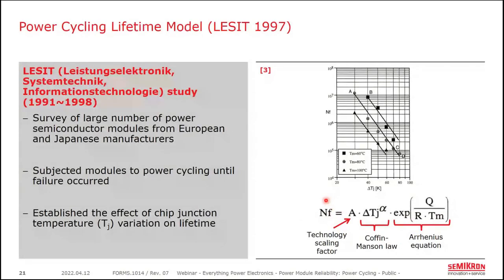And if we plot this, we see that here on the x-axis is the delta TJ here in Kelvin. And on the y-axis is the number of cycles to failure. And you see there are three different lines here. The dots represent actual experimental points, but these three different lines are for three different mean junction temperatures. And because this is a logarithmic scale on the x-axis here, you can see that it's the delta TJ that really has that strong influence on the number of cycles to failure.